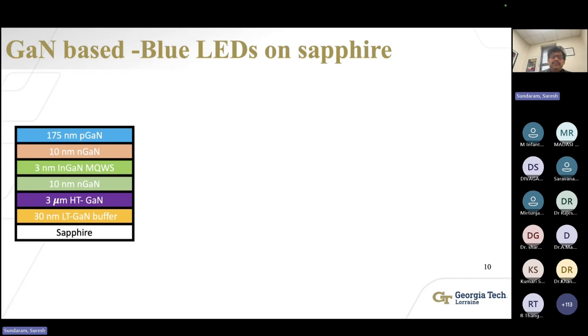This is the typical structure of a blue LED. We start with a low temperature gallium nitride buffer on top of sapphire. This acts as a wetting layer, and then we grow a 3 micron high temperature gallium nitride layer. The growth temperature is close to 1080 degrees C. And then we grow MQWs, where we incorporate 3 nanometer thick indium gallium nitride multi-quantum wells, which are the light emitters.